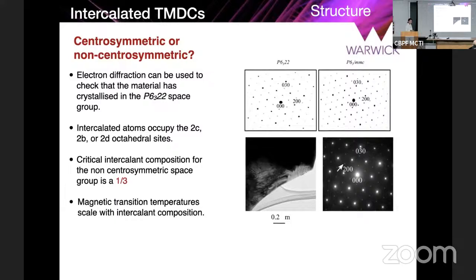But the very first step in this is to establish whether the crystals that we have produced crystallize in the non-centrosymmetric space group. Now, I've shown you all the information about the intercalated concentration of one-third in these. So this is the magic critical composition at which there is a transition from the centrosymmetric to the non-centrosymmetric space group. And we need the non-centrosymmetric space group here in order to see the chiral soliton lattice and to see a helimagnetic ground state. So how do you establish whether it's centrosymmetric or non-centrosymmetric?